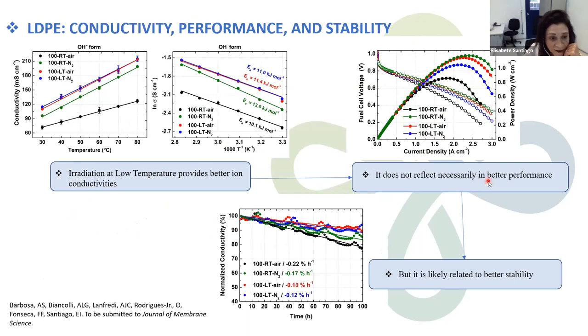So in terms of conductivity, performance, and stability, you can observe that membranes irradiated at low temperature present high conductivities, but higher conductivity does not necessarily reflect in higher power densities. For example, AEMs irradiated in nitrogen at room temperature and low temperature present quite similar performance. However, membranes irradiated at low temperature present better stability, or lower conductivity losses. Summarily, irradiation at low temperature provides better ionic conductivities, but that does not necessarily reflect in better performance, but we have obtained very good stabilities for materials produced under such conditions.